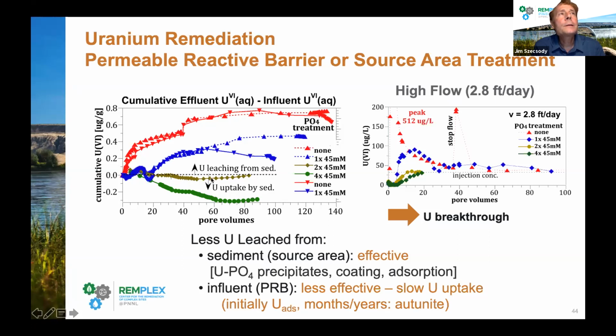By the time you got to this level of treatment, the plot is showing us that this level of treatment worked very well as a source area treatment because essentially no uranium was leaching from the sediment. But with even higher phosphate treatment, some of the uranium that was flowing into the column was actually taken up. So this is hinting that the phosphate could act as a permeable reactive barrier. That's what's shown on this left diagram.